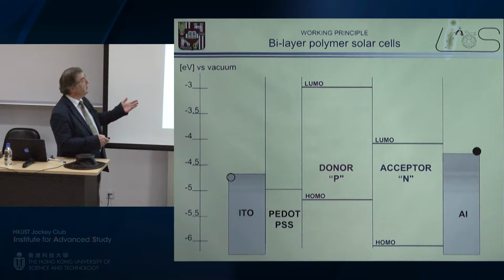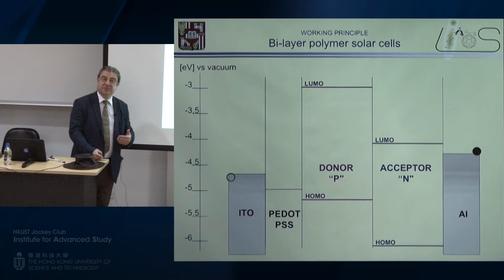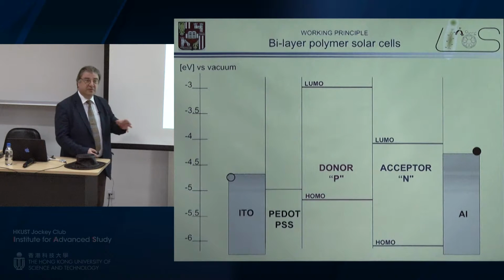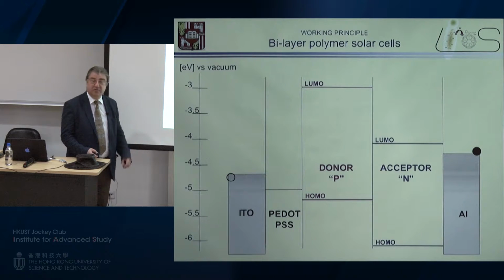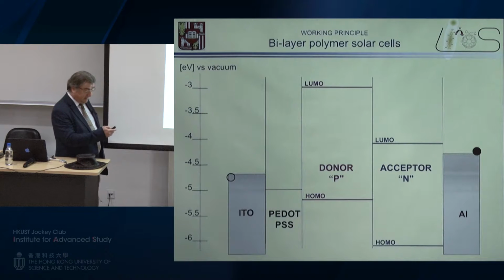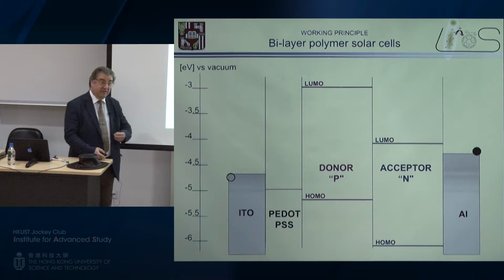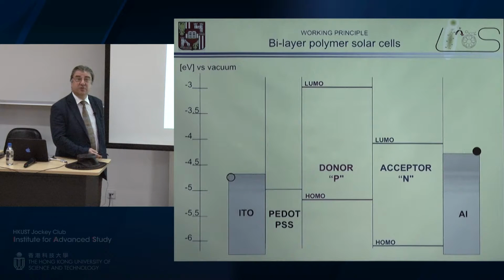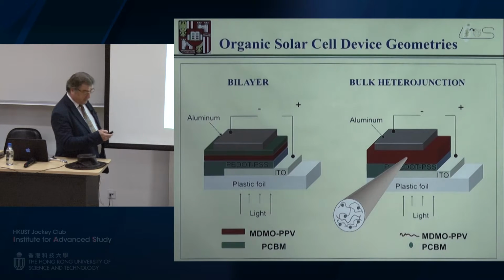But you see immediately here the shortcoming: the exciton diffusion length to the acceptor interface is only of the order of 10, 15, maximum 20 nanometers. So these films have to be really thin, in the thickness range of the exciton diffusion length, which is tough. I mean, to structure something on a 10 nanometer scale is tough even for UV lithography. So our contribution was this, let's say, bulk heterojunction, which is possible if you have something soluble, processable.